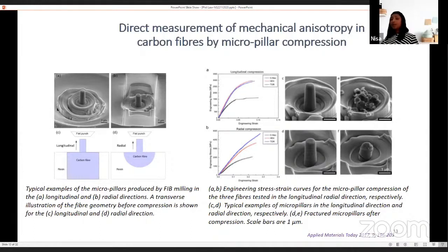So to address these issues, we came up with an approach. It's a very simple and direct method to measure the transverse and longitudinal properties of carbon fibers through micropillar compression. Here is a typical example of the micropillars made by focused ion beam milling, both in longitudinal and radial directions. And here are the fractured micropillars after the compression.